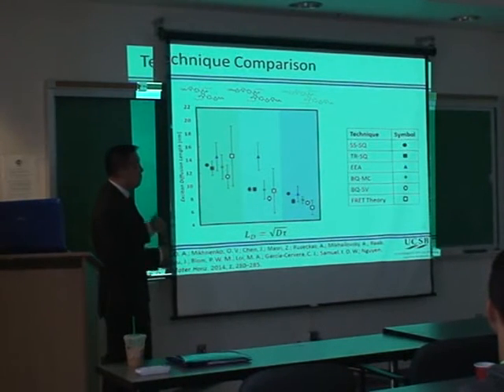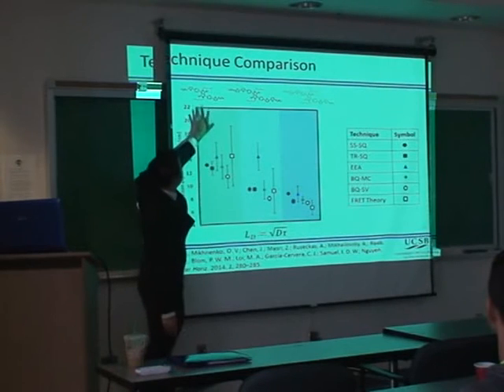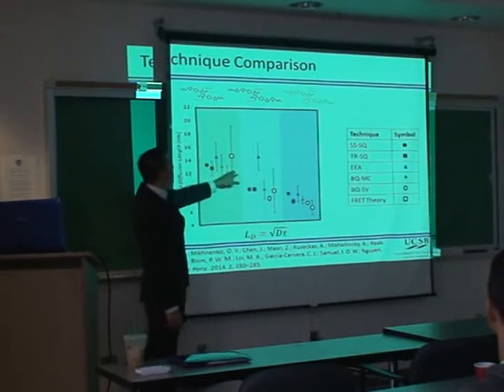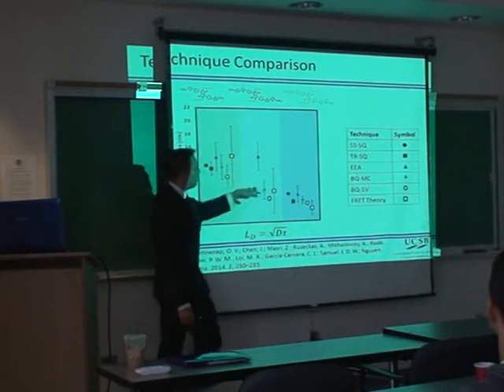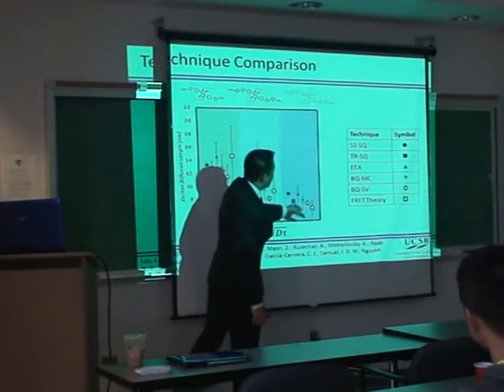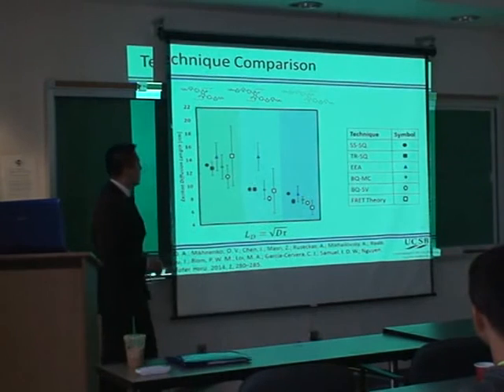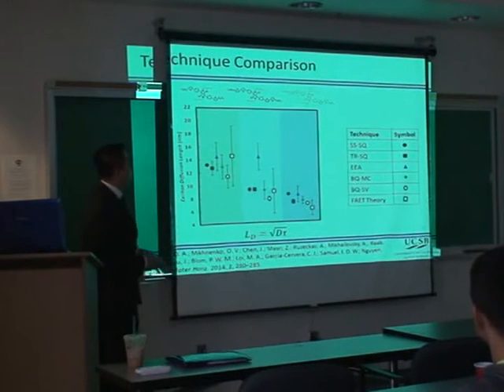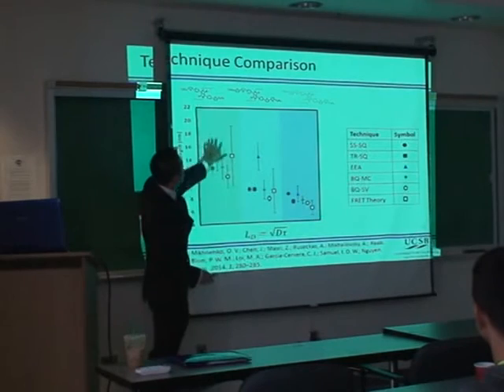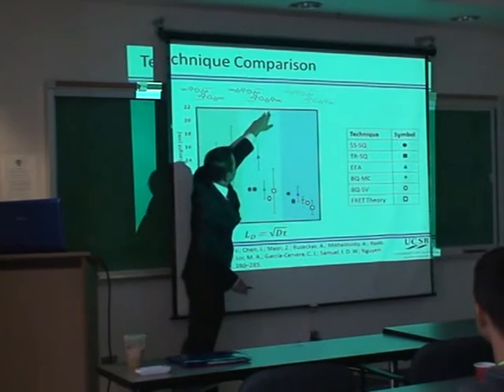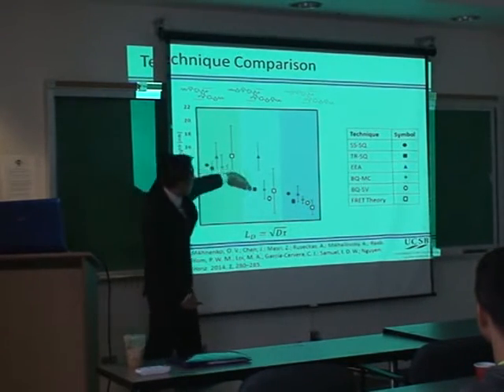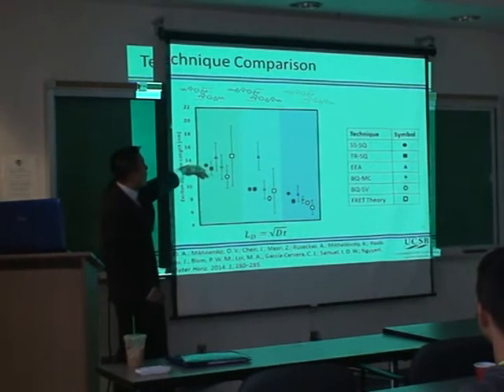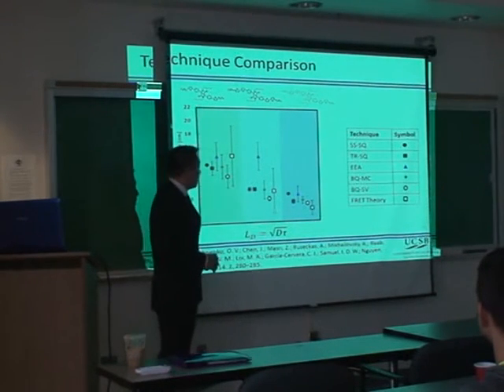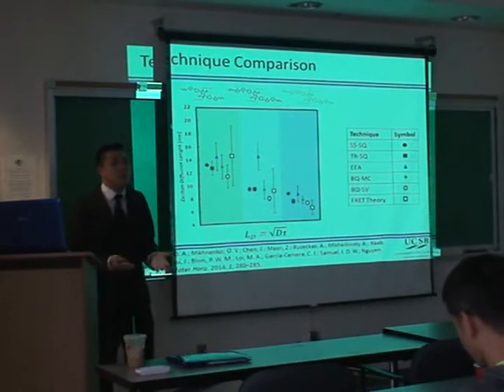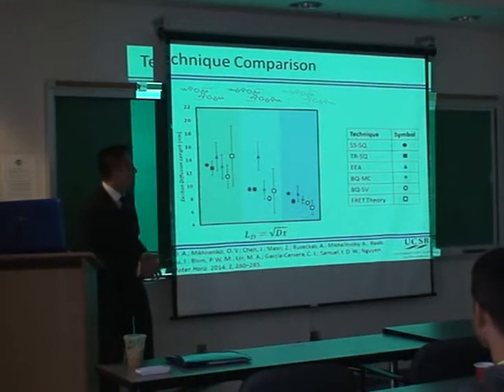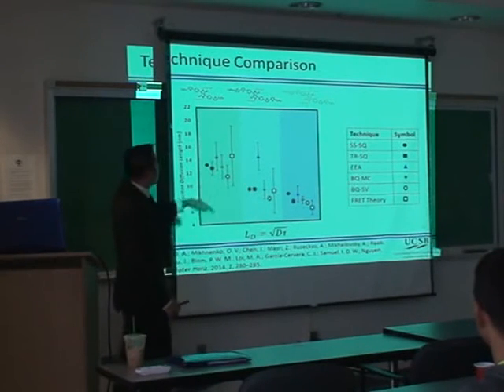And that morphology will change what exciton diffusion length you will measure. So the conclusion is that, if you're going to work with crystalline materials, you have to be careful about comparing different techniques. It's maybe only good to compare amorphous materials between different techniques. The next thing we could do, now that we've compared techniques, is compare chemical structure, these 3 together. And what we see is this trend downwards. One thing we found is that this correlates pretty well with the crystallinity. We did some X-ray diffraction measurements and measured the order in the film, and we see that this trend correlates with the order in the film.